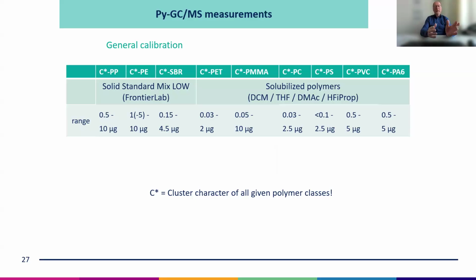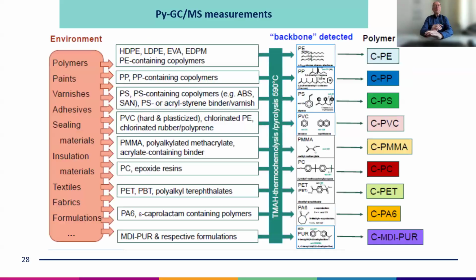That means that some polymers have similar indicators, and you have to put them in a cluster. The next problem for the quantification is that you have a lower and a higher detection limit. You always have a range, and this range is different for every cluster. It can be 30 nanograms per gram for PET, and for example for polyethylene only 1,000 nanograms, or 1 microgram per gram. So it's different, and the indicators for polyethylene and for PVC are always in discussion.